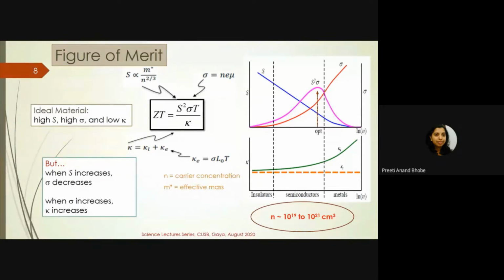Whereas conductivity, we know, increases as the number of carriers increases. And similarly, K electronic will increase with conduction electrons. K lattice will not get affected so much; it will remain almost stable compared to the change we see in K electronic. So depending on all these three factors, it was found that an ideal increase in ZT can be obtained when you have a carrier concentration between 10 raised to 19 and 10 raised to 21 per centimeter cube.